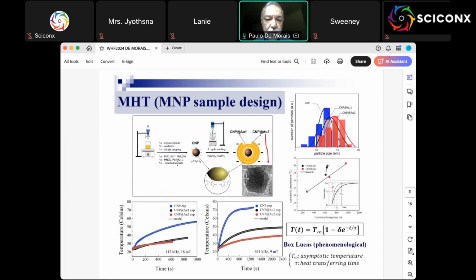So in terms of sample design, let me show you one example. In this example, we took standard magnetic nanoparticles, maghemite, and then we coated maghemite with a thin layer of gold. And actually, we produced two samples. The first sample has a very thin layer of gold, and in the second sample, the surface layer was thicker. So we have two samples.